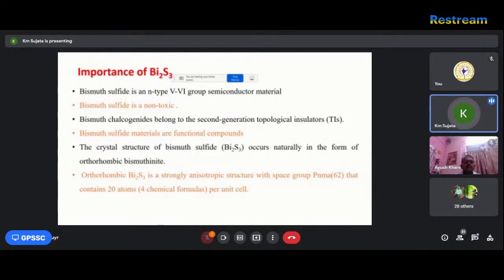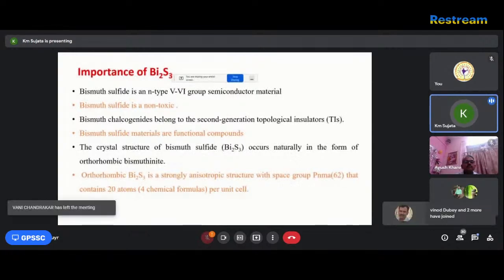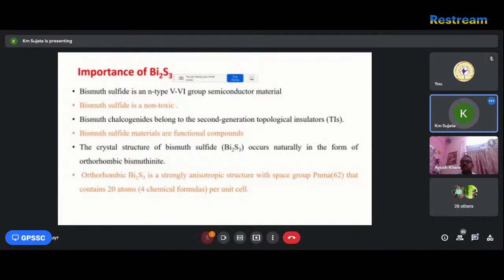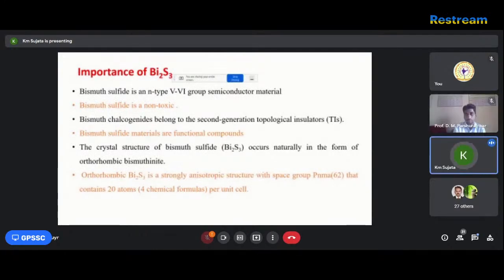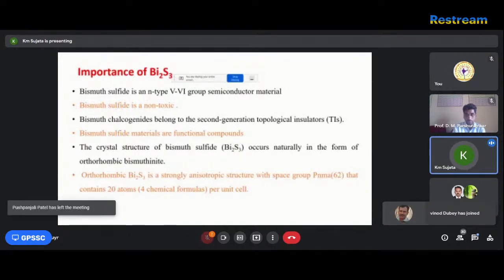Bismuth sulfides belong to the second generation of topological insulators, as they have an insulating bulk gap and a conducting state on their surface due to strong spin orbit interaction, which involves the orbital character of conduction and valence band. Bismuth material is a functional compound and a very attractive material for a wide range of applications such as photovoltaic, thermoelectric, photocatalytic activity, micro and optoelectronic devices, photoelectrochemical and infrared detectors, but my aim is for thermoelectric application.